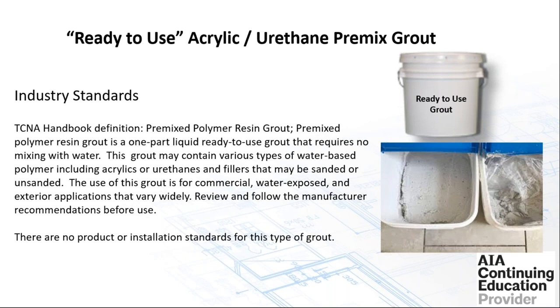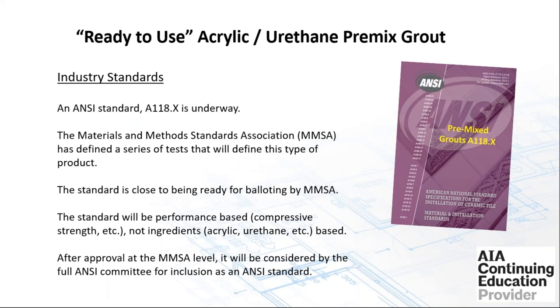Ready to use urethane grouts, urethane acrylic grouts. These are very, very popular these days. We'll get to the pros and cons in a minute. This grout may contain various types of water-based polymers, acrylics, or urethanes. It can be used in a commercial application. Exposed to water or submergible applications, it really comes down to the manufacturer; follow the technical data sheet, but in most commercial applications, it can be used. There are no standards for this particular grout as of yet. However, it is becoming very popular, and the standards are in the works. They're going to be based on compressive strength, not ingredients. We're working on the standard through MMSA, and that will be considered by the ANSI committee for inclusion.